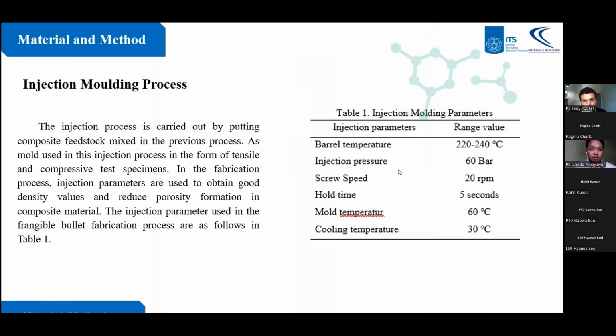The second step is the injection molding process. The injection process is carried out by putting in the composite feedstock mixed in the previous process. The mold used in this injection process is in the form of tensile and compressive test specimens. In the fabrication process, injection parameters are used to obtain a good density value and reduce porosity formation in the composite material. The injection parameters used in the frangible bullet fabrication process are shown in Table 1. So this is the injection molding parameter to make the frangible material.